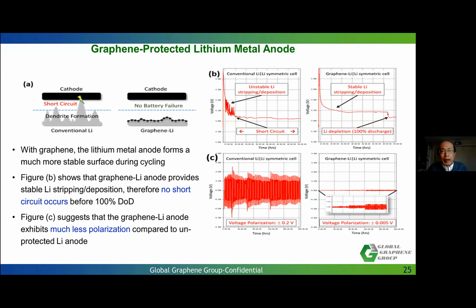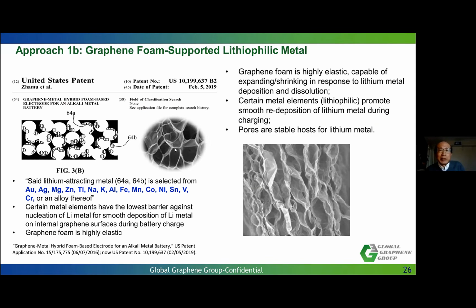The second approach that we use is the so-called graphene foam. In other words, we introduce what we call lithiophilic, or lithium-attracting, metals such as silver and others into the internal site of the graphene foam. The graphene foam itself is a highly elastic structure, so it will expand and shrink when your lithium metal shrinks or expands. That will help you maintain a good contact between the lithium metal and the solid state electrolyte.